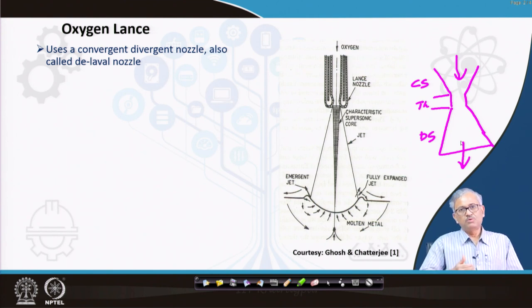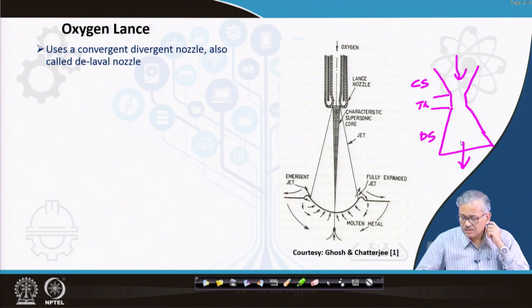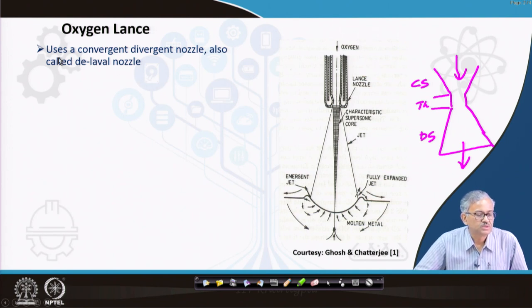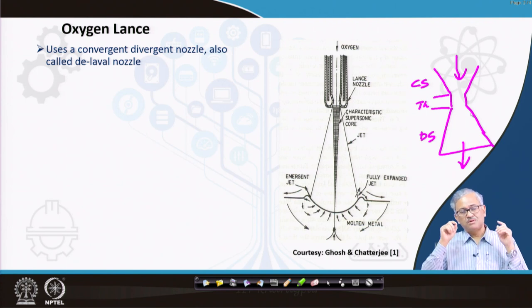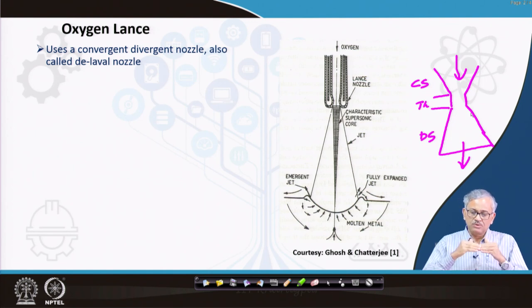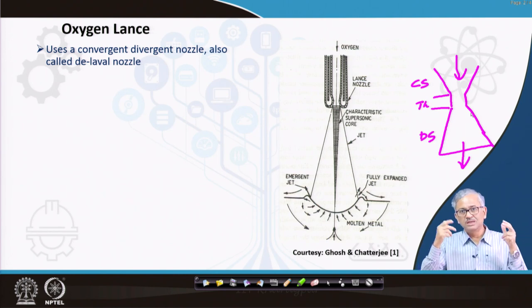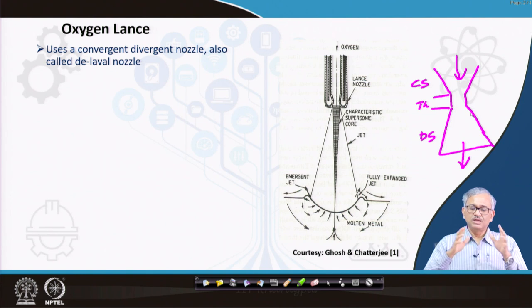So, the jet will progress through the atmosphere. Obviously, it will enter the surrounding atmosphere like this. Okay, so this is the advantage. You are basically using a convergent-divergent nozzle, and that has the capability of accelerating the oxygen, or producing an oxygen jet, at supersonic speed. And when the gas comes out of the convergent-divergent nozzle, its pressure is almost equal to the ambient pressure. That's why the interaction with the atmosphere is not very large. As a result, shockwave generation is not possible here. So, your energy dissipation is not there.